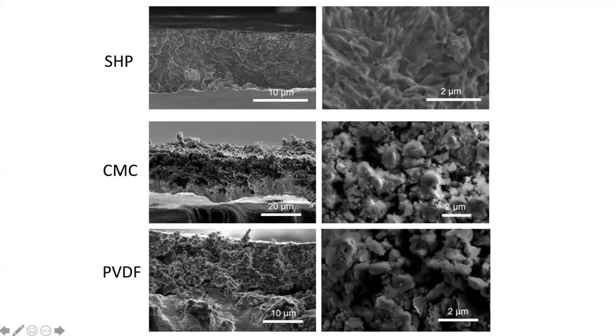And the other thing is the fracture causes a lot of newly exposed surfaces. So every charging, discharging, when new surface is exposed, there's an electrochemical reaction that can take place and slowly eat away the silicon and convert it, together with organics, into some kind of insulating product that's no longer active for storing lithium. So this shows the strong contrast of using self-healing material and these other polymers. So this was the very beginning of work my group started in exploring self-healing polymer for battery applications. And currently this concept is being explored by various other research groups around the world to look at other types of related polymer designs.